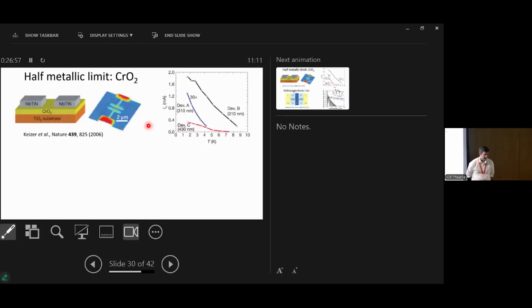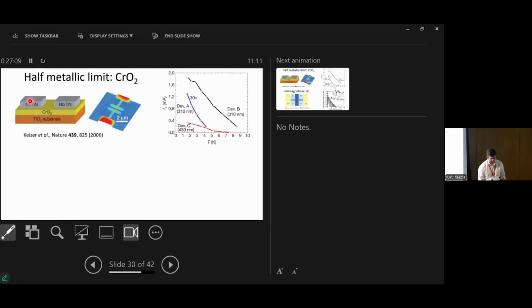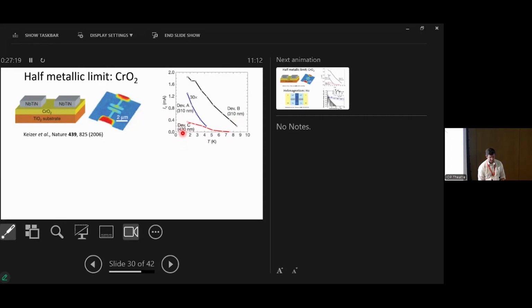So the first probably convincing realization of this was from the Delft group, where they used chromium dioxide between two superconductors, and they could see a supercurrent passing through chromium dioxide over very large distances. For me, hundreds of nanometers is a huge distance. You remember from the previous slides, we were seeing supercurrents over a few nanometers. This is 2 orders of magnitude larger. So these Cooper pairs pretty much had to be triplet Cooper pairs because chromium dioxide is a half metal. It only carries one type of spin. So there must have been something funny going on at these interfaces to convert the singlets to triplets.